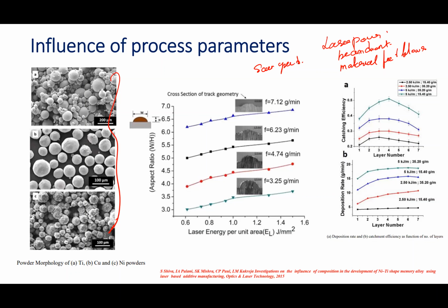The shape and deposition of the tracks are governed by two combined parameters: the laser energy per unit area and the powder feed per unit area. The laser energy per unit area depends upon the beam diameter on the substrate surface as well as the scan speed. The shape of the track geometry was investigated in terms of the aspect ratio as a function of the laser energy per unit area. The experimental observation confirmed the formation of non-uniform discontinuous tracks under certain onset values of powder feed per unit area.